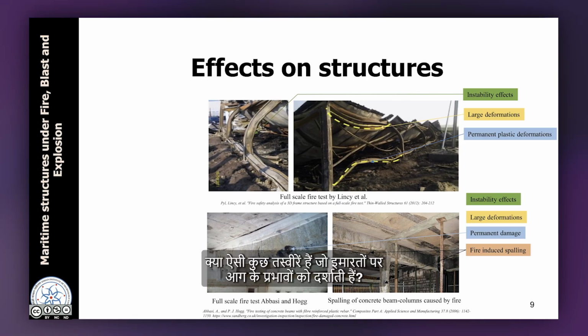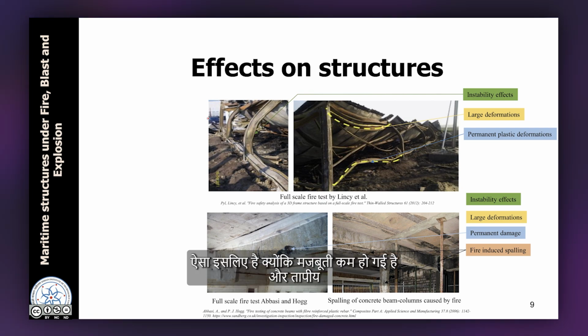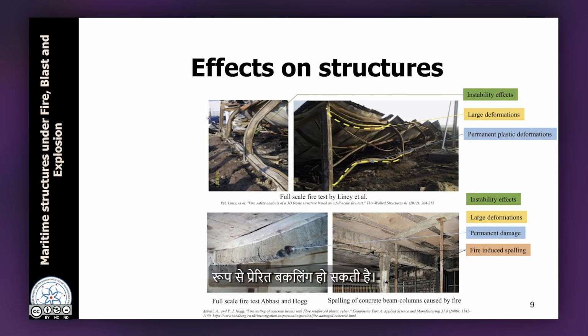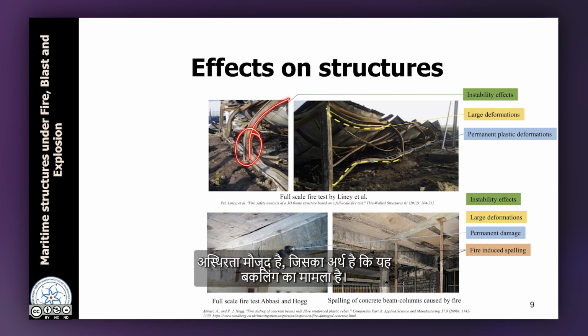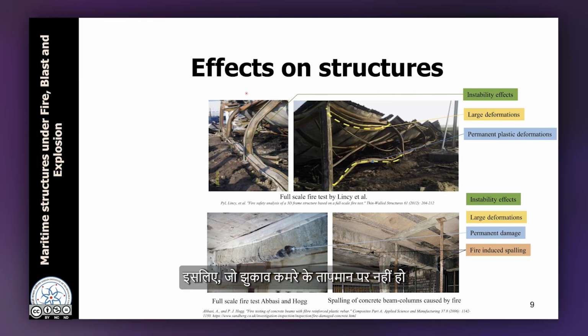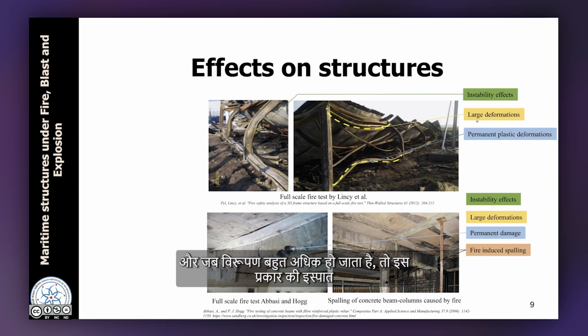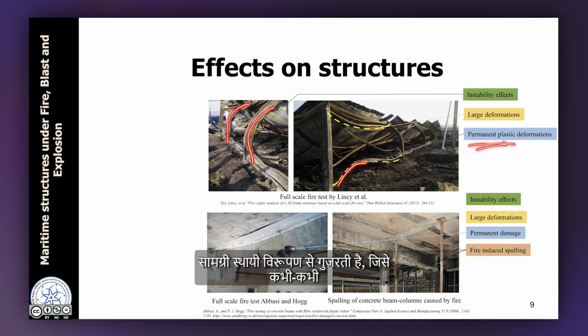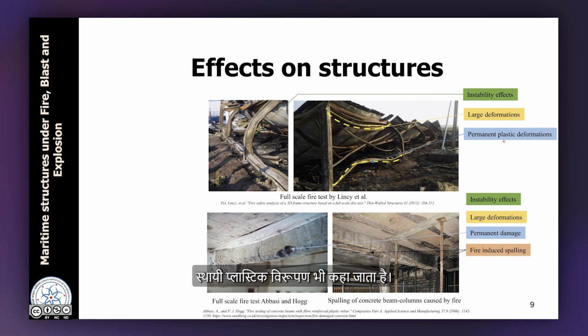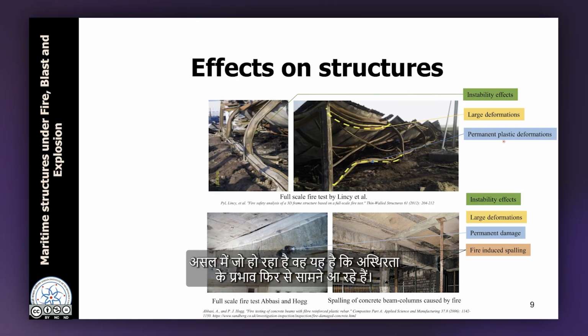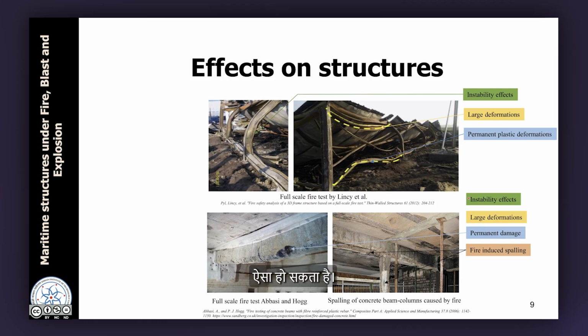These are some photographs which show the effects of fire on structures. The top two photographs are of steel structures. What is very visible is that there are very large deformations, extremely large deformations. This is because the strength has reduced and thermally induced buckling may have happened, thermally induced additional bending may have happened. So there are very large deformations. There is instability, which means this is a case of buckling. So buckling which was not happening at room temperature has happened at a high temperature. And when deformations become very large, these steel materials undergo permanent deformations, or sometimes also called permanent plastic deformations.